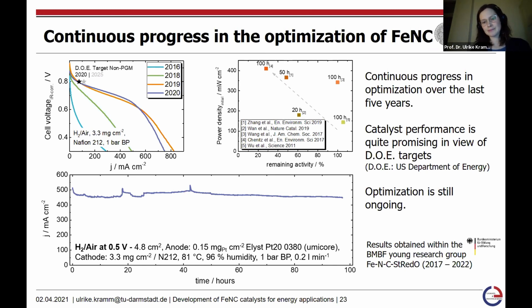Okay. Typically, with any transition metal catalyst, when you really look at long term, there's always some kind of corrosion or dissolution because the electrolyte is still acidic in nature. So most of them have much lower stability, as is also shown here.